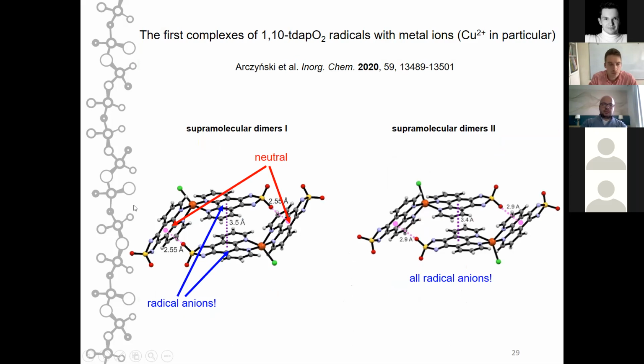So in the case of the supramolecular dimers 1, the pi-pi stacking interactions are controlled by the radical anions, and these side ligands are actually neutral. In neutral dioxothiadiazole, the central ring is indeed very pi-acidic. That's why the part of the radical anion that has some additional electron density, due to the additional electron that is placed on this molecule in the radical state, forms this kind of very short interactions, 2.55. This is one of the shortest distances in this kind of sigma hole configuration.